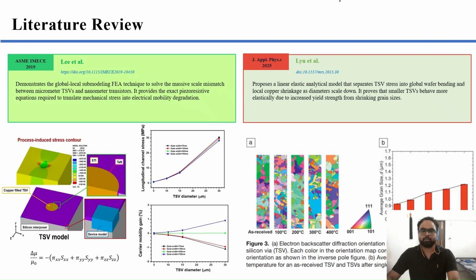each thermal cycle. This colorful strip image is a microscope map of copper grain structure inside a TSV. Each color represents a different crystal grain orientation from left to right. You can see how the grains become fewer and larger as the temperature increases from room temperature through 100, 200, 300, and all the way to 400 degrees Celsius. The bar chart on the right quantifies this: average grain size grows from 0.9 micrometer in the as-received state nearly to 1.2 micrometer after cycling to 400 degrees Celsius.